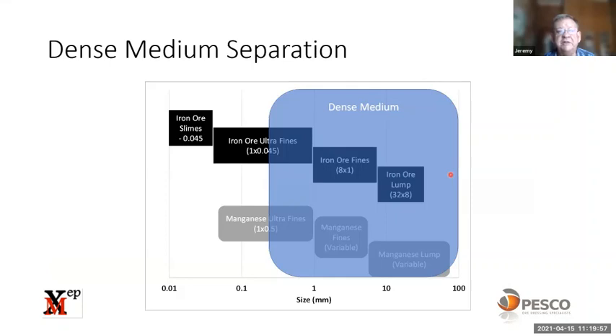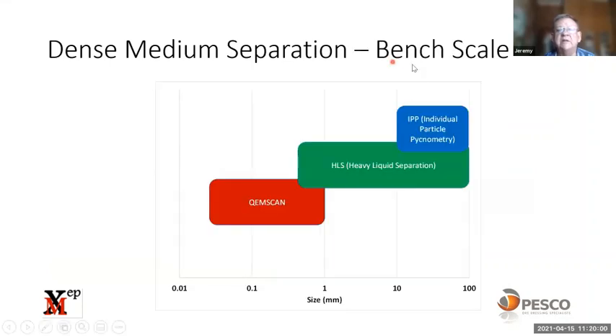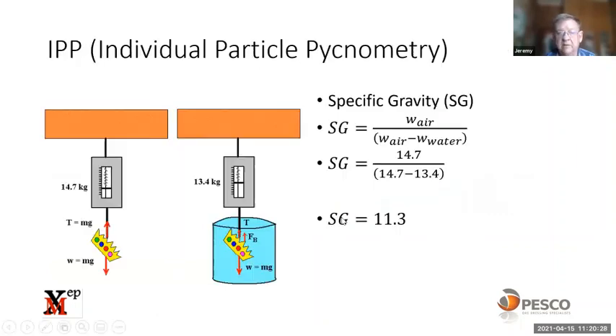We'll focus on dense medium and the dense medium bench scale. What we find is that we've got 3 techniques that we can use on bench scale for dense medium. We can use individual particle pycnometry, we can use heavy liquid separation, and we can use QEMSCAN. You can see the individual particle pycnometry is valid above 10 millimeters. Heavy liquid separation can go down to 0.5 millimeter, and then QEMSCAN is typically on -1 millimeter. If we look at individual particle pycnometry,